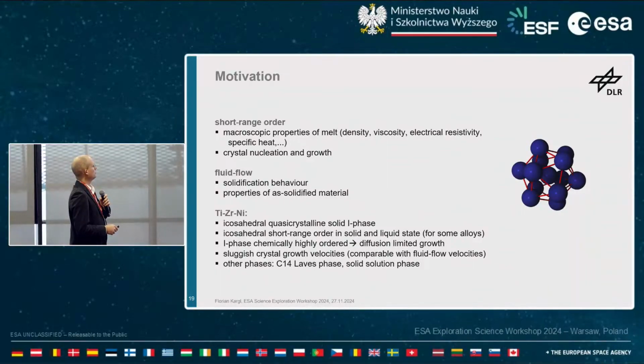The background to this is short-range order in the system and an idea to look into macroscopic properties of the melt, so density, viscosity, electrical resistivity, and specific heat, how this develops in the system when you start to undercool it. And we will see that there is really an impact. And there might be a relation between what the structure is doing in this system and how the macroscopic properties are reacting. And then one is also looking into crystal nucleation and growth in the system.